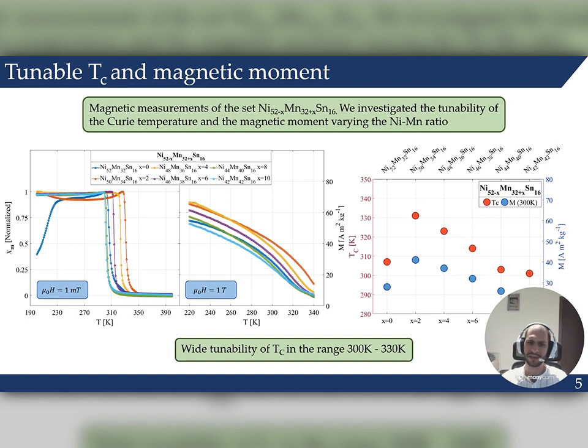The reason why we decided to report them at this particular temperature is because we think that, given the application of the energy harvesting of low-grade heat, their values at room temperature become particularly relevant. To summarize the results, we can observe the wide tunability of the Curie temperature of this set of samples, which covers the temperature range between 300 Kelvin and 330 Kelvin. And this is, in our opinion, one of the reasons why we think that Heusler compounds are very promising candidates for energy harvesting application.